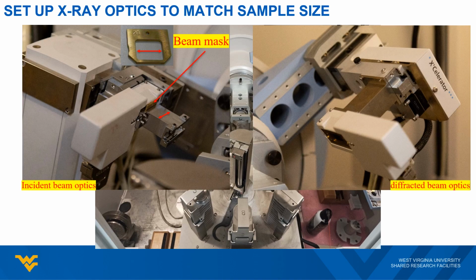Beside this beam mask, there are two automatic programmable slits: the divergent slit on the incident beam side and the anti-scattering slit on the diffracted beam side. The divergent slit will determine the X-ray illumination length on your sample, and the anti-scattering slit will determine the X-ray collection length from your sample. Those two slits are exactly the same type of device, but on different sides of the sample, and they are controlled by the data collector software.